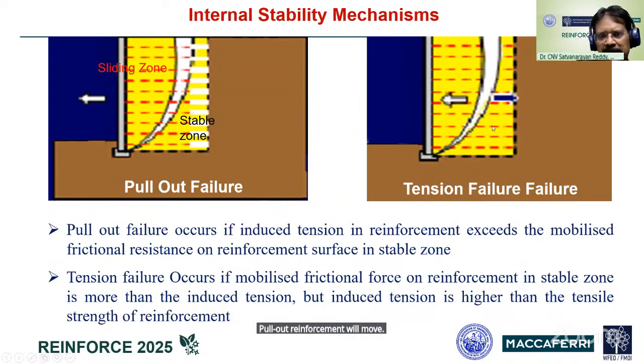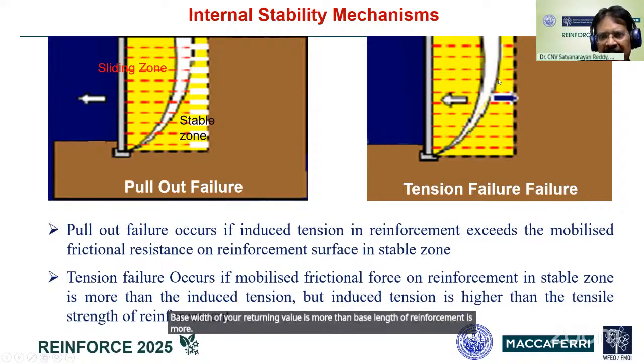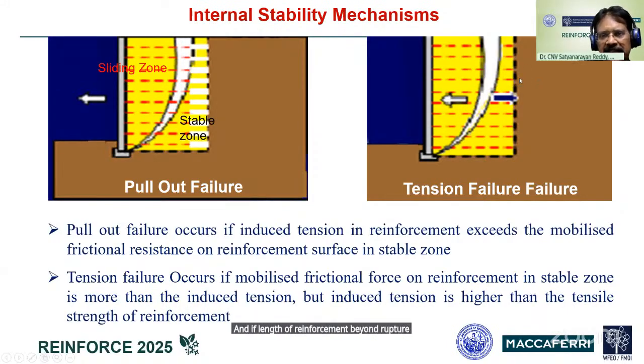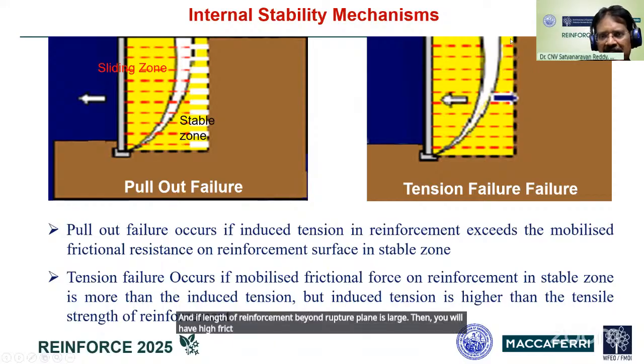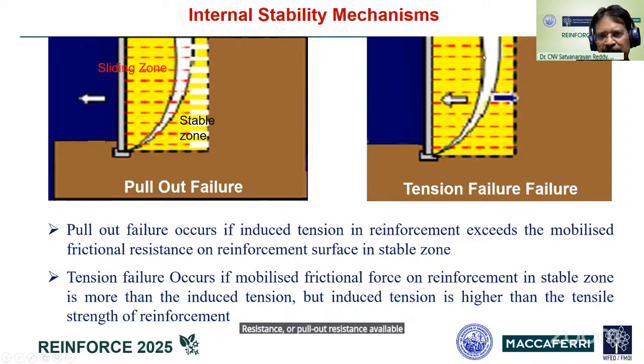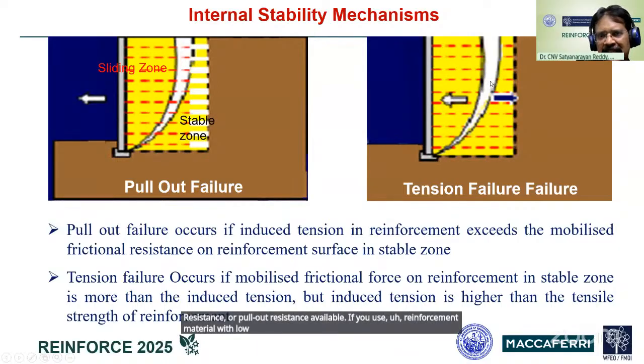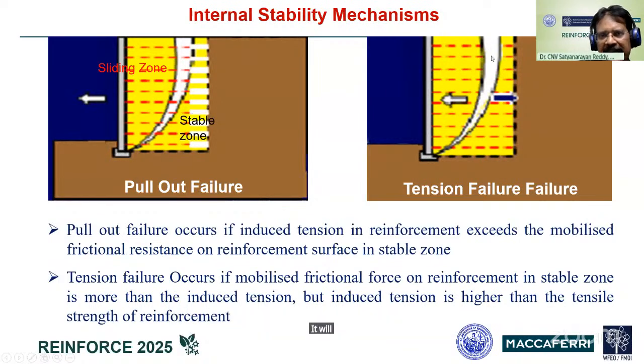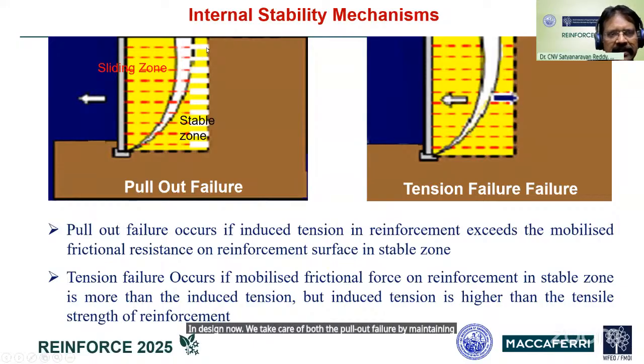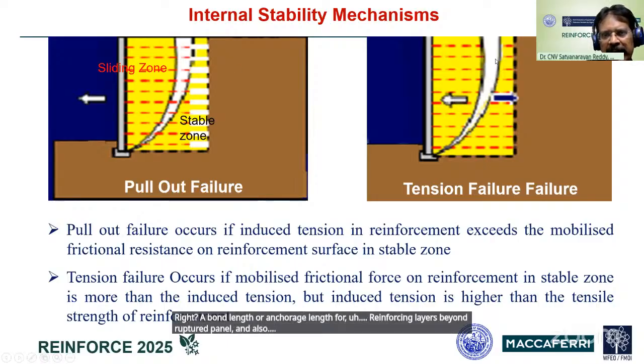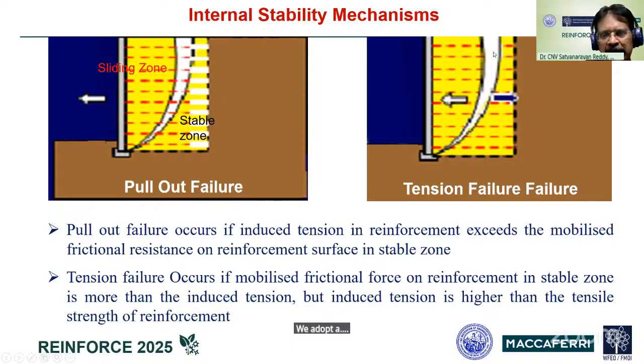If the provided base width of your retaining wall is more, that means the length of reinforcement is more, and if the length of reinforcement beyond the rupture plane is large, then you will have high frictional resistance or pull-out resistance available. If you use reinforcement material with low tensile strength, the possibility is it will break, right? That is called tension failure. So in design, we take care of the pull-out failure by maintaining adequate bond length or anchorage length for reinforcing layers beyond the rupture plane, and we also adopt the ultimate tensile strength of the reinforcing material in such a way that tension failure does not happen.